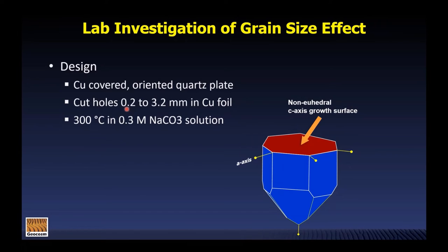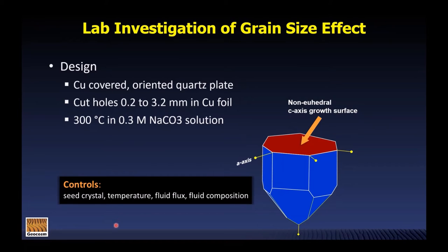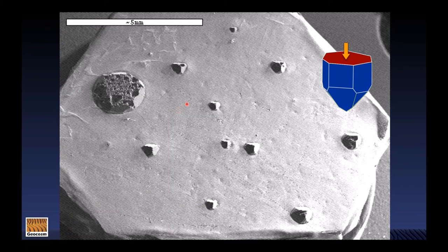And so the neat thing about this experiment was that we had so many controls. We were growing overgrowths on the same seed crystal. These overgrowths were growing from the same temperature and compositions of fluids. And really, the only thing that we were varying was the size of the new nucleation domain. And so to take a look at this, this is an SEM photomicrograph. We're kind of looking down on the top of this quartz plate here. These little guys here are overgrowths that have begun to grow through this copper foil.